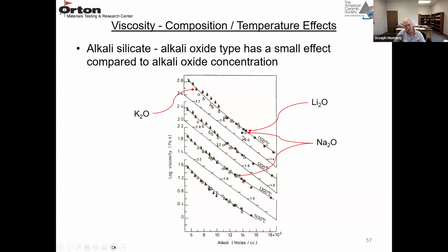So no matter what temperature it is, you can see the viscosity decreases with increasing alkali content. And then as you increase the temperature, you're going in this downward direction. The viscosity is decreasing also. So whether it's K2O, Li2O, or Na2O, you see they're all falling on these curves. So the type of alkali doesn't really affect the viscosity as much as the concentration of the alkali.